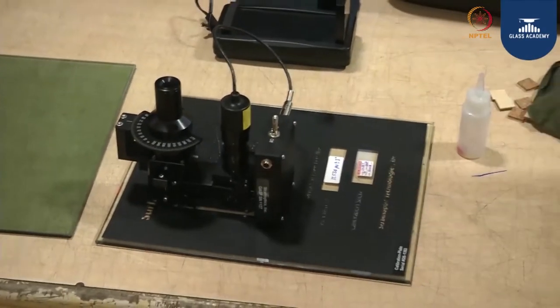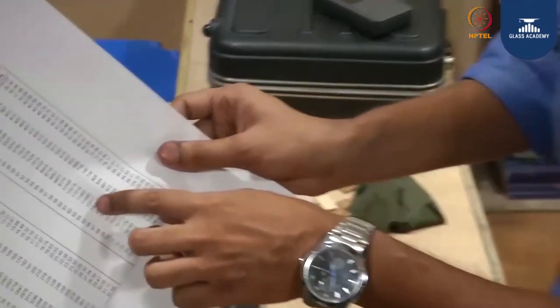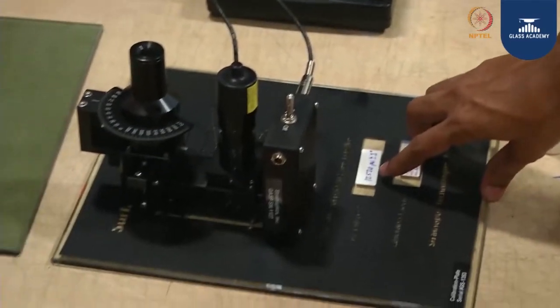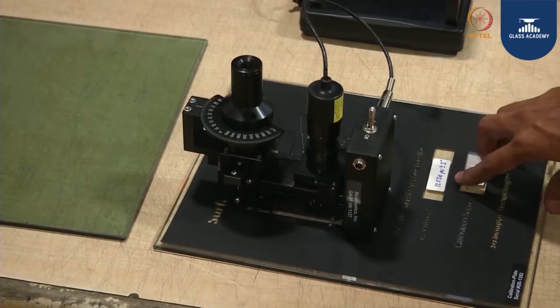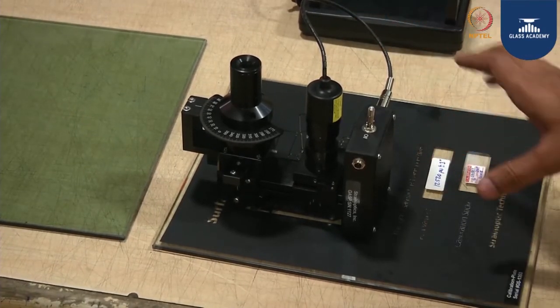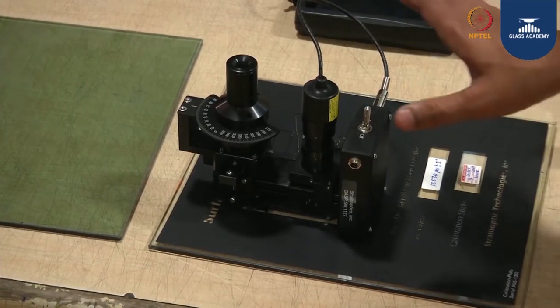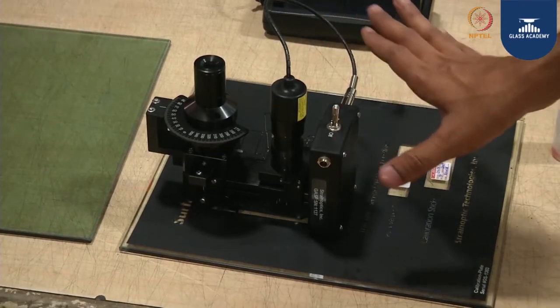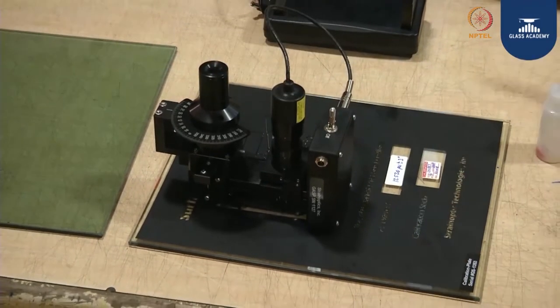The stress lines are colliding at a 64 degree angle. As per the 64 degree angle here, the reading is 12517, whereas we are getting 12520. So based on the self-calibration of this plate and this equipment, we can say that the equipment is calibrated. Now we will see this on actual glass.